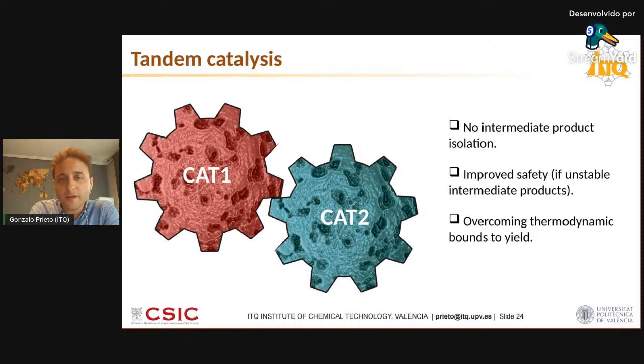Tandem catalysis has a number of benefits, such as, for instance, the fact that we are avoiding the need to isolate and purify intermediate products in between different conversion steps. That saves energy and cost. It may even improve the selectivity and even the safety of some processes when a very reactive or even unstable intermediate product, which is produced by a first reaction, is processed in situ on the second catalyst very shortly after it forms, so reducing its average residence time in the reaction medium.